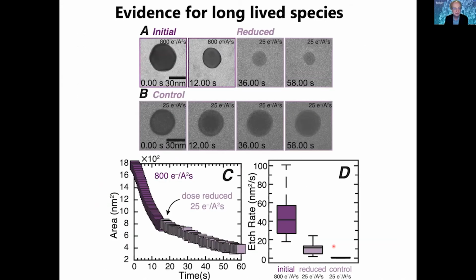The other thing we were able to do is an experiment in the electron microscope, where we create that highly oxidized iron species, and then we simply turn off the electron beam. When we do that, we see that the etching actually continues for a very long time. There would be absolutely no etching if we had not first introduced the electron beam, and of course, the iron is required. At this very low dose rate, it's enough to be able to see the particle, but not enough anymore to do any of the chemistry that would normally modify it. It means that the species, like the one created in the pulsed radiolysis, must also be present here and is continuing to perform the etching after the electron beam has effectively been turned off.